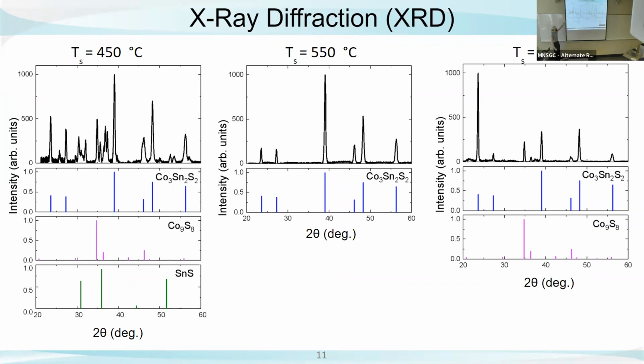And so if you look at our intensity versus 2 theta, this is our raw data on the top in black. And then the fingerprints for other materials are listed underneath. And so when the peaks line up, you can tell that that is in our sample. So the blue peaks line up, but there's also multiple peaks that don't line up with that shandite structure that we want. So we know there are other materials within it, which is why there are a couple more listed below to fill in those peaks that weren't identified in that shandite fingerprint.